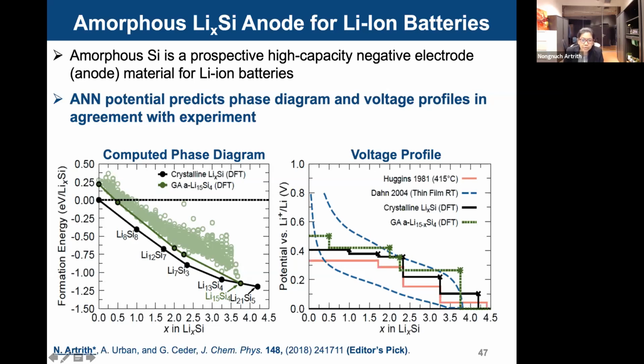And here we show the computed phase diagram, where we can remove a lot of lithium from the structures, and then we find what the most stable structures are. So this is how we computed it using our neural potentials. In this case, I only show the DFT results because the neural network predicts as good as DFT. And we also compare our predictions of different phases with the experimental voltage profile. So our neural potentials also predict good agreement with the experimental voltage profile here.